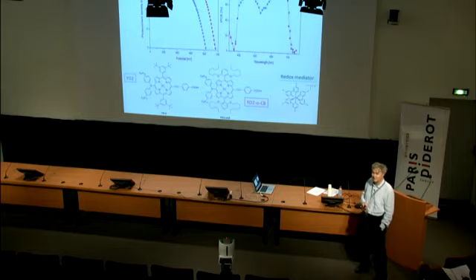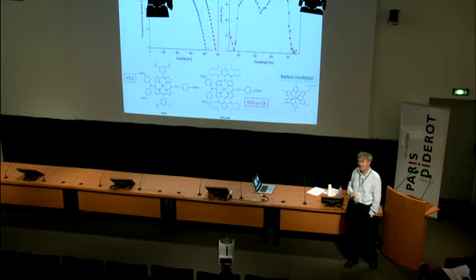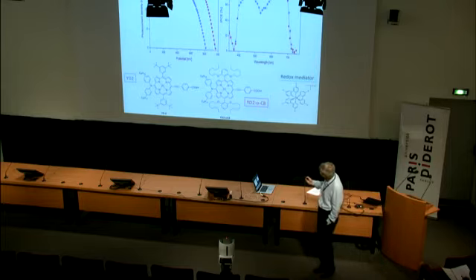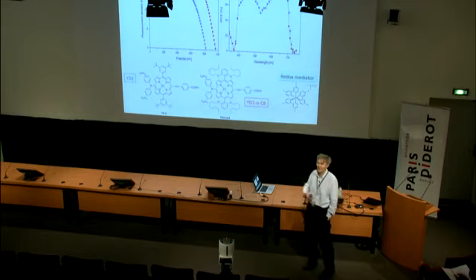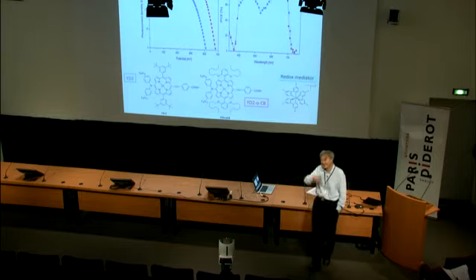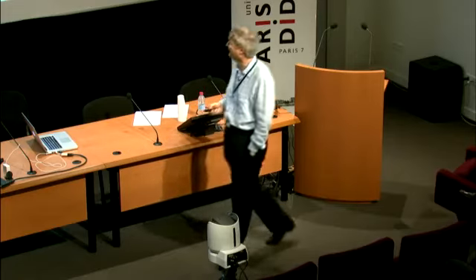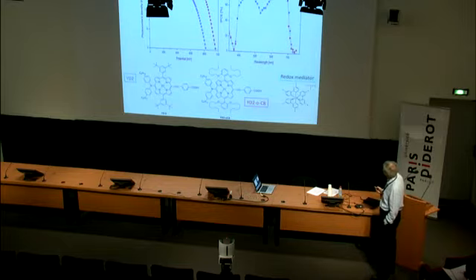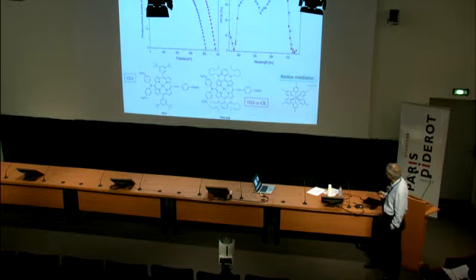970 millivolts VOC, open circuit voltage. For us, it was a dream to get this high open circuit voltage. It comes along with a high current. Of course, if you don't have a high current, then the highest voltage doesn't help you, because the efficiency is the voltage times current times fill factor. And you can also see here the IPCE spectra, much better for this alkylated or alkoxylated dye.